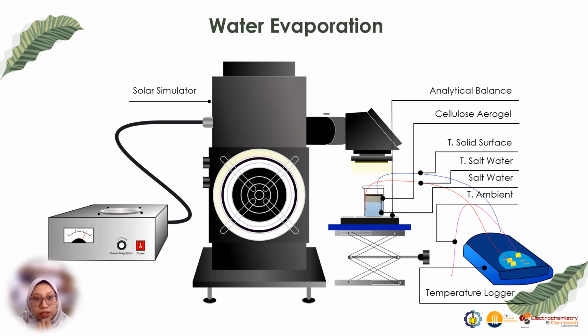Water evaporation experiments were carried out using a solar simulator and a 300 watt lamp at room temperature. The prepared SSG system consisting of cellulose aerogel and ink was put on the surface of salt water in a 50 milliliter beaker glass. The salt water contained 3.5% sodium chloride. The beaker glass was placed on the top loading balance to measure the weight change of water evaporation.